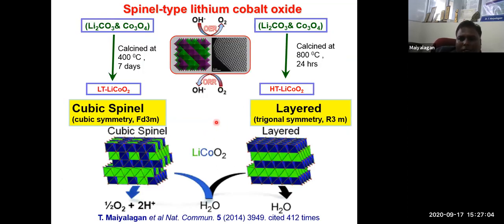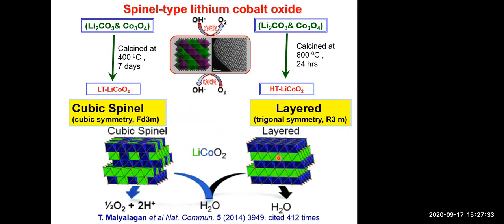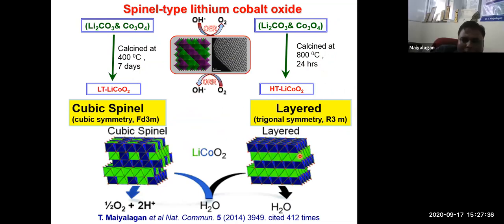This is a lithiated spinel. There are two forms here. Just take lithium carbonate and cobalt oxide, grind it, and calcine at 400 degrees centigrade for 7 days. You get a low temperature spinel. The same material, heated at 800 degrees centigrade for 24 hours, gives the high temperature layered structure, which is what you use in your lithium-ion batteries. This material is used in lithium-ion batteries because of the layered structure, where lithium insertion and extraction take place very fast. So we want to evaluate these two materials for oxygen reduction and oxygen evolution.